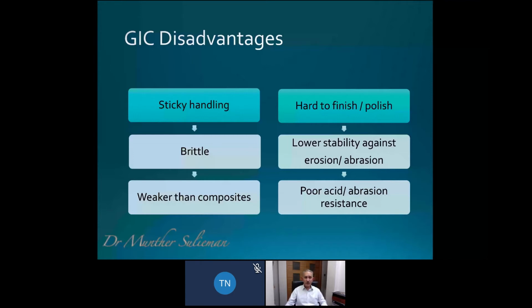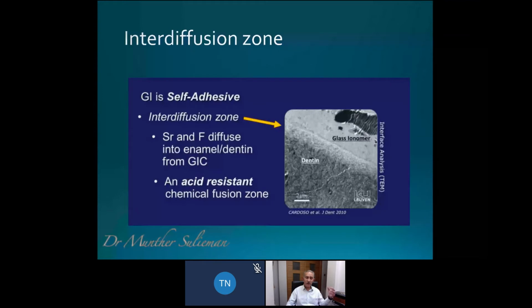Now, if you remember, I said to you about ion exchange one way and the other. The ability of strontium and fluoride to diffuse into the enamel and dentine actually gives you a very good marginal seal and gives you a very good acid-resistant chemical fusion zone one way, and then the other way, as I said, from the tooth, the calcium and phosphate ions incorporate into the cement. So it gives you a very, very good bond.